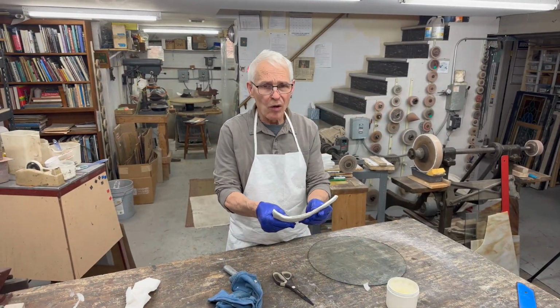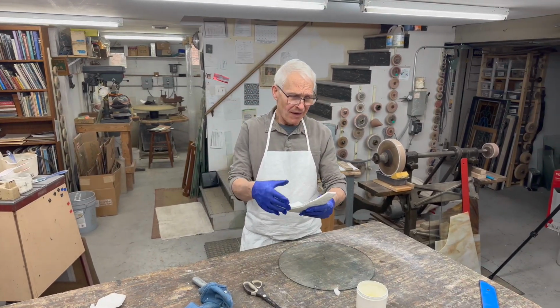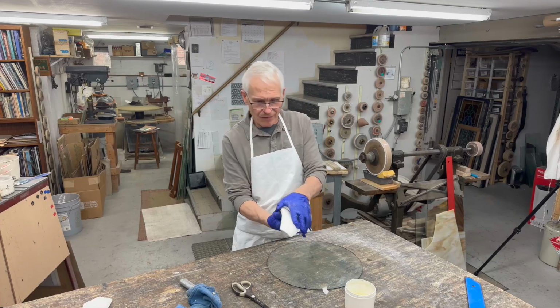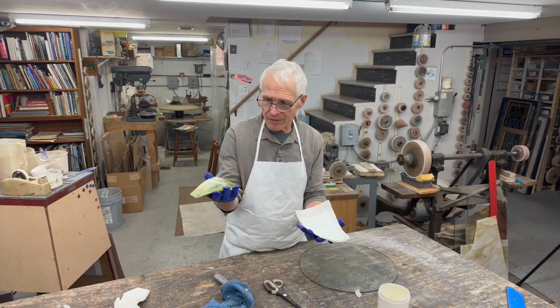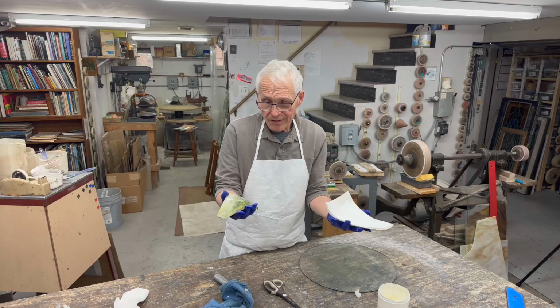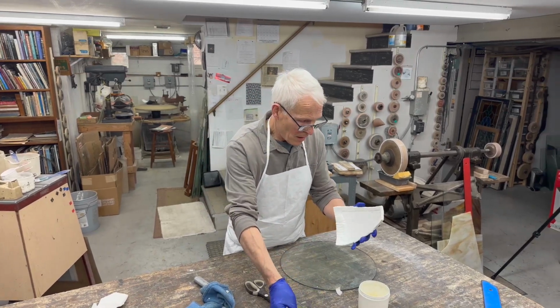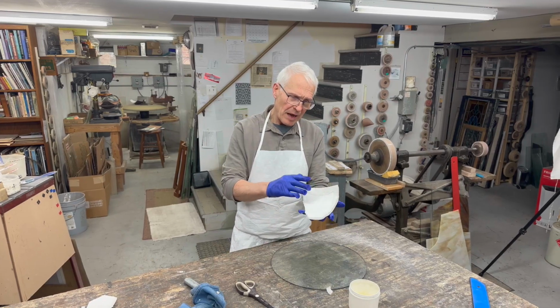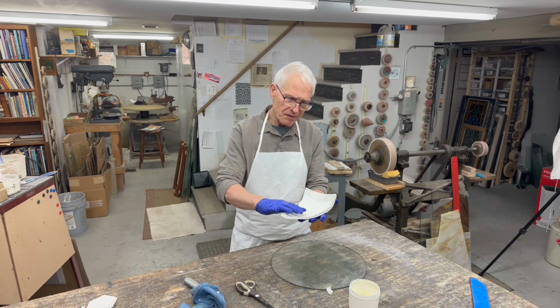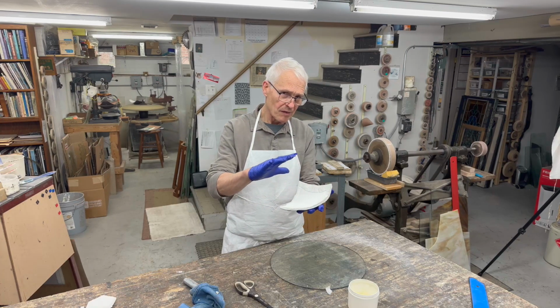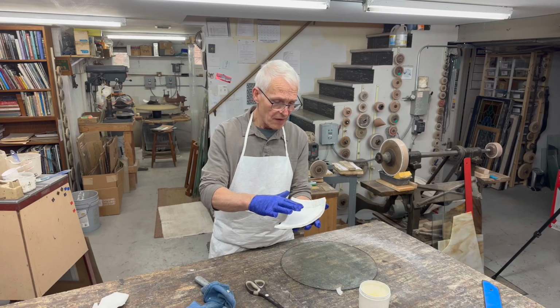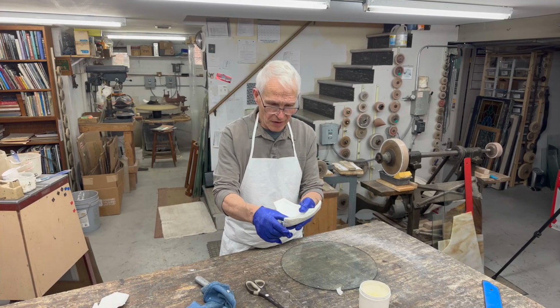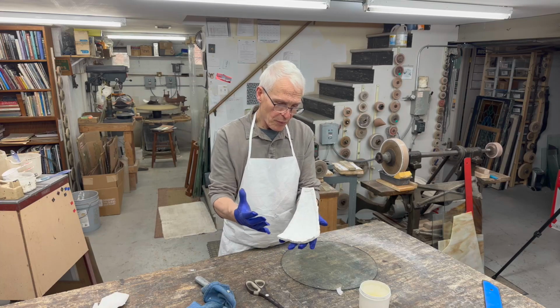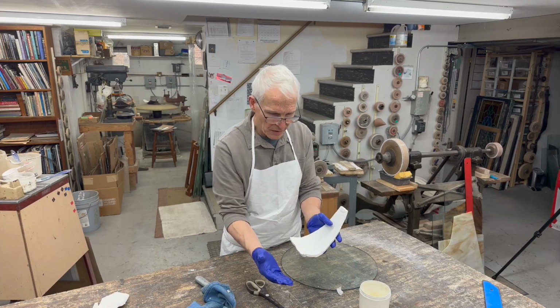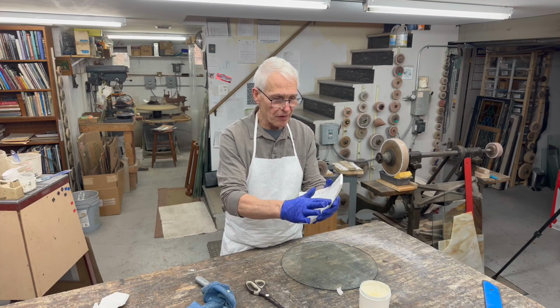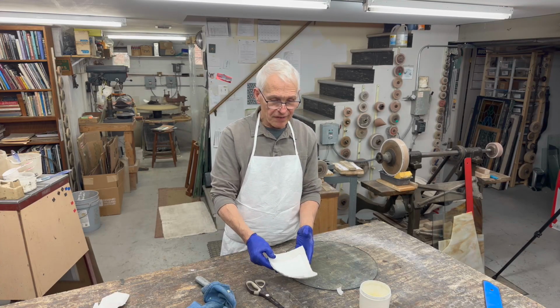So we've got our mold, it's dry, it's hard, and we can pull it. It'll come right off because it was covered with grease or Vaseline. The only thing we have to adjust before we put a release on this, so that the glass blank won't stick to it in the kiln, is a little bit of a ridge that developed because we pushed the wet blanket down over the glass. We have to sand that down.